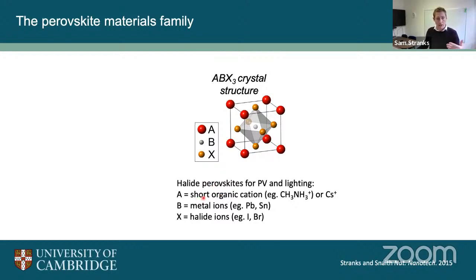And so when we think about the solar cell materials, at the A site, usually we have small organic cations. These are small organic molecules that contribute here, or cesium ions as well. In the B site, the metal, we have typically a cation such as lead or tin, and in the X site we have halide ions, so iodide or bromide typically. And so these are the typical absorbers or emitters that we are working with.